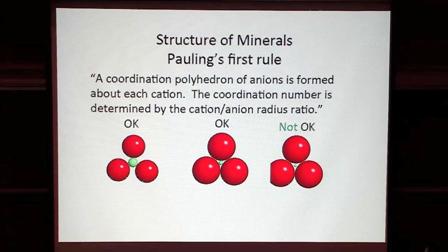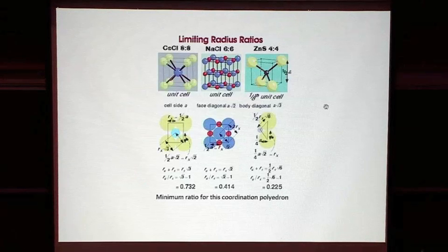The basic rule is that the cation can't be so small that it rattles around in the anion cage, and as a consequence, depending on the size of the cation to the anion, one gets different geometric arrangements of the anions around them. And this is governed by basically the cation-anion radius ratio, the so-called radius ratio. And depending on the radius ratio, we get different geometric arrangements. So these are the limiting ratios of the cation radius to the anion radius.